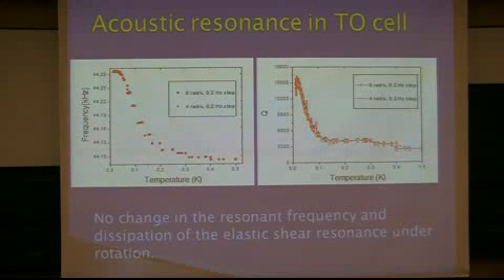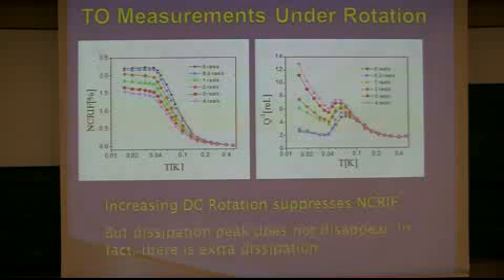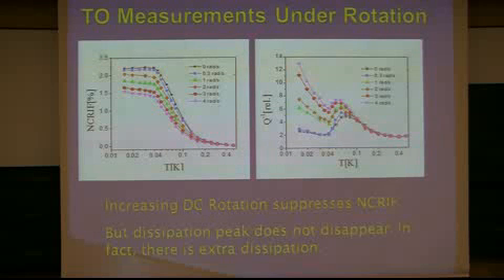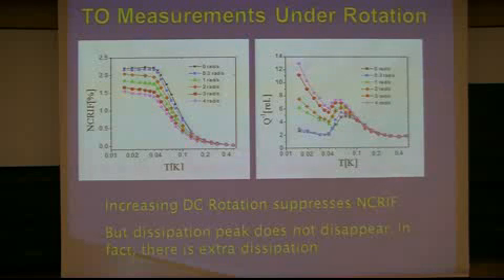Then how about the torsional oscillator response? If the torsional oscillator response is due to the elastic modulus change, we don't expect any change in the torsional oscillator response either, right? So who said you don't believe in the supersolid? Let me show you the experimental result. With DC rotation, there is strong suppression in the non-classical rotational inertia, meaning disruption of supersolidity. With just this sufficiently slow rotation, it is extremely difficult to understand this kind of phenomenon without using superfluidity.